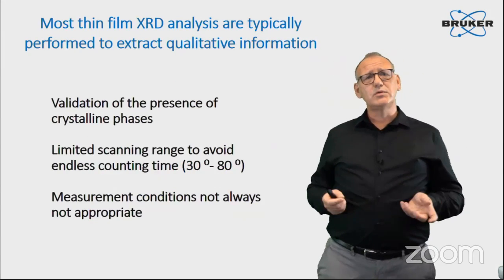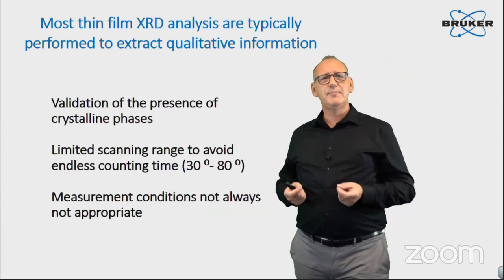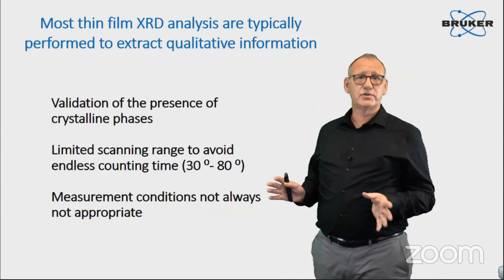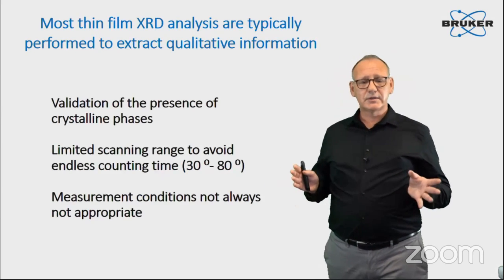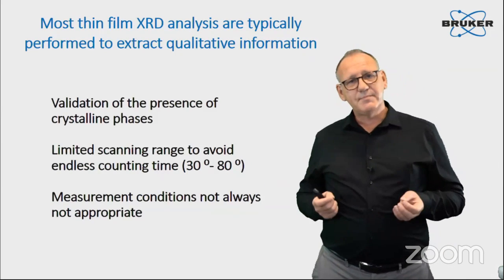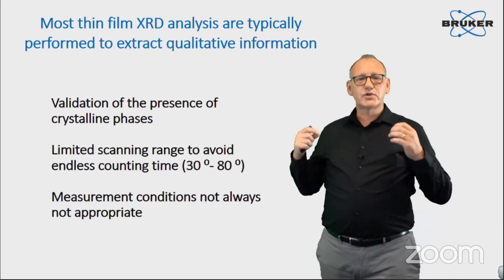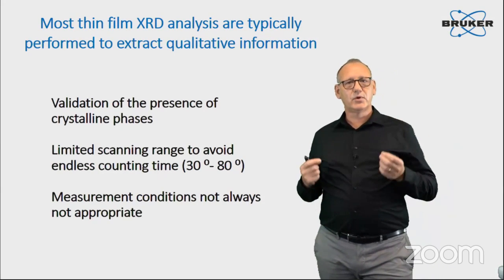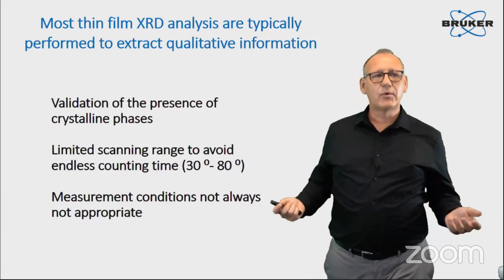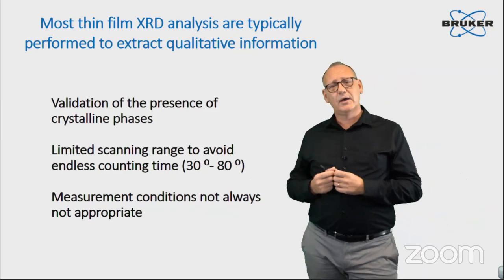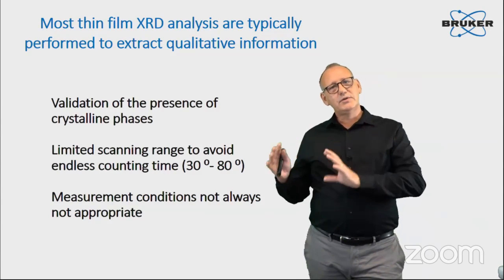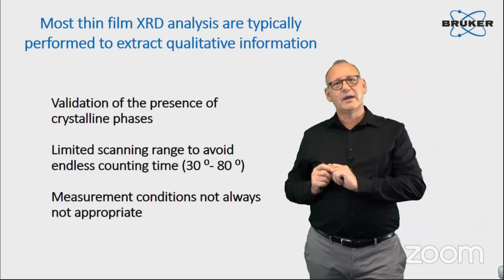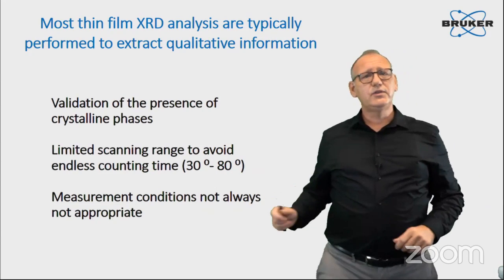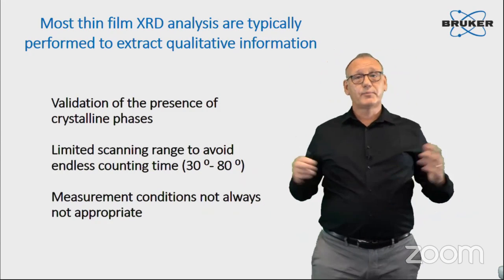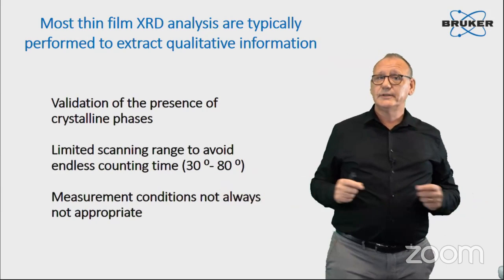My point is that most thin film XRD analyses are typically performed to extract qualitative information. People run these measurements because they are so challenging. There is so little material that you don't want to measure endless time to have a good scan, because you know it will take you hours or days if you don't set up the right measurement approach. So they use it to validate the presence of a phase, and it means that they actually measure on a pretty small scanning range, 30 to 80 degrees, while probably your diffractometer can cover a much wider range.